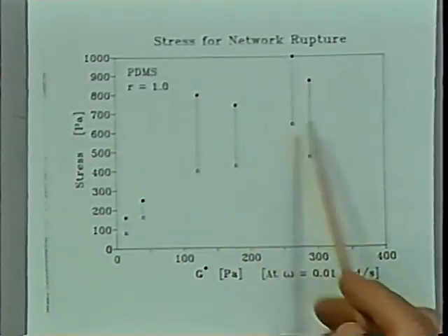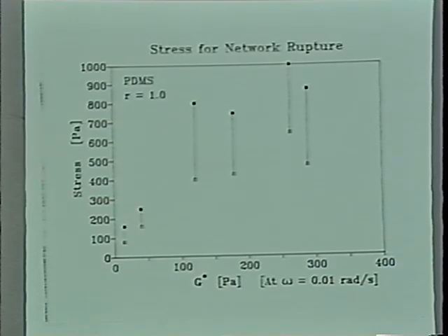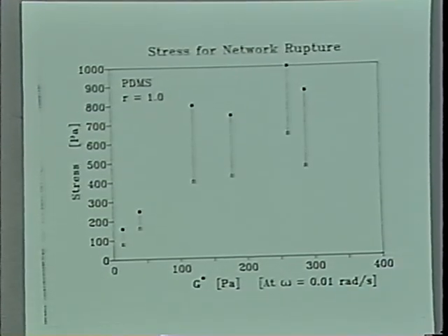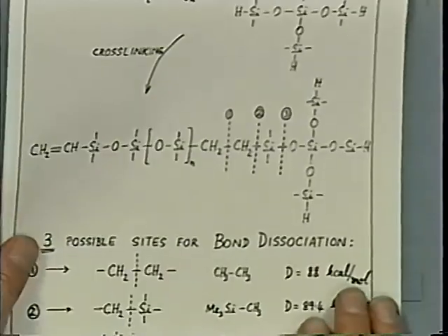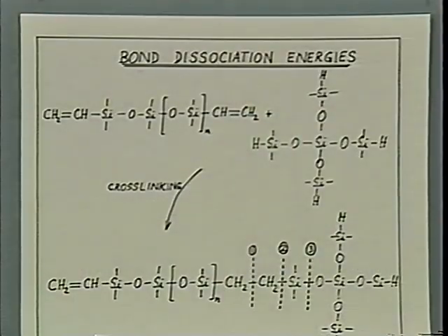The scatter is tremendous because you're leaving continuum mechanics in that experiment. You're really breaking something. You're producing some wild response in the material and get some statistic errors to whatever you're doing. But the general tendency is, I think, understandable. The bonding energy has been reported in the literature. The bonding energy for our PDMS gels.